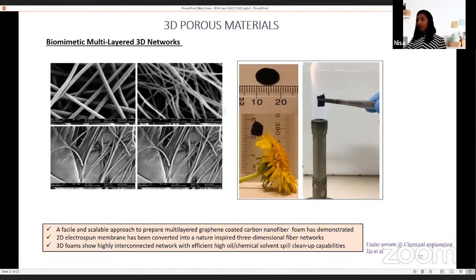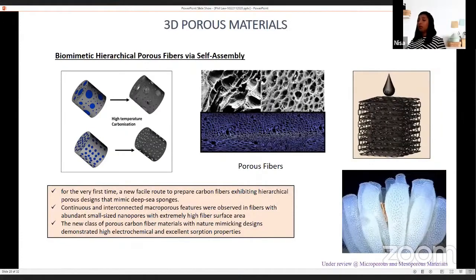capabilities. We also wanted to look at what will happen when we scale up self-assembled nanostructures at macro scales. So we have demonstrated this to make functional fibers. So here we designed marine sponge-like functional fibers. So these fibers exhibited meso, micro, macro-sized porous features, both on the surface and the cross-section of the fibers. And these fibers exhibited high surface area. And we also checked the adsorption and energy storage properties of these fibers.